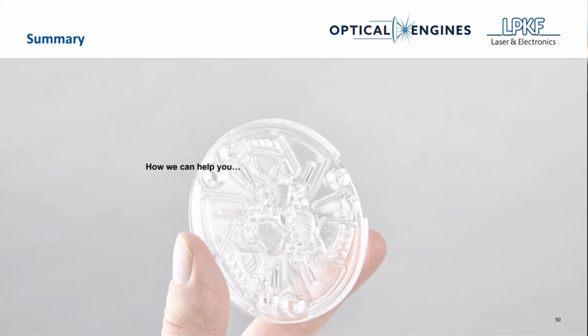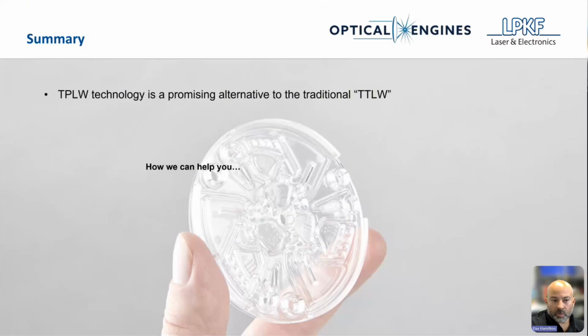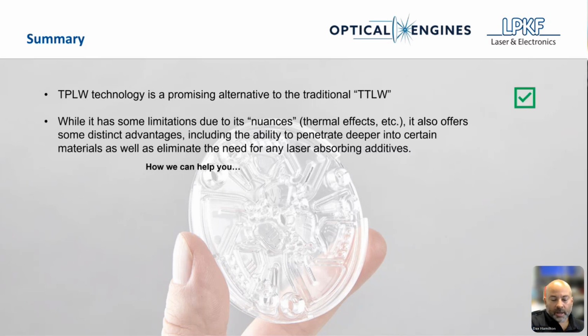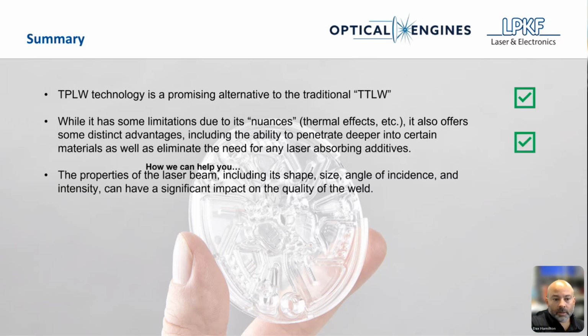We'll go into a quick summary here. That didn't come through. Well, I apologize. Transparent polymer laser welding is a promising alternative to through transmission laser welding. I think that we all can agree on that. It has limitations, like I said: thermal effects and volumetric absorption, which also helps us in certain ways, deeper weld penetration, and it eliminates the need for any laser absorbing additives, and you can keep the plastic in its natural state. And the properties of the laser beam, including shape, size, angle of incidence, and intensity, can have a significant impact on the quality of the weld. So again, one of the advantages to transparent polymer laser welding.